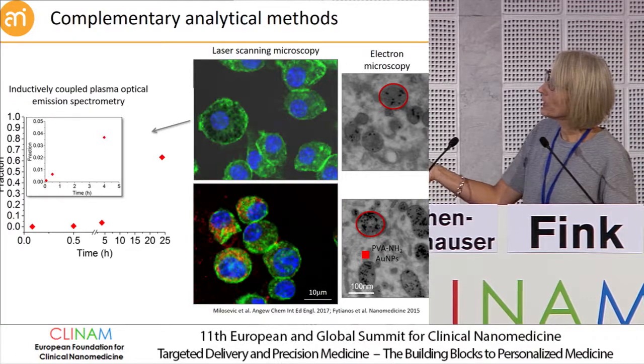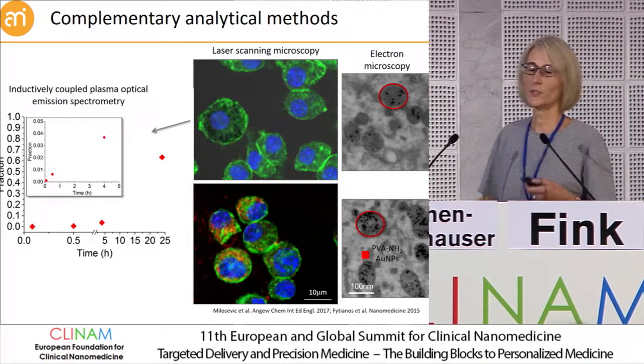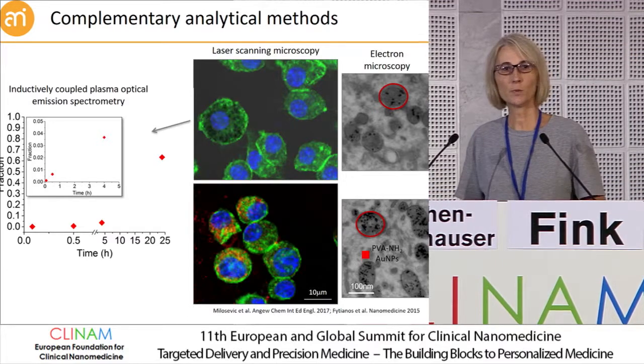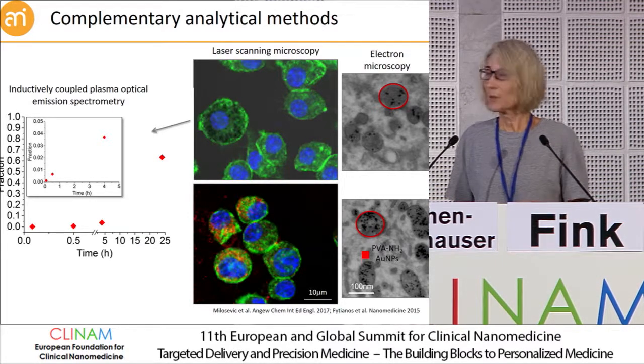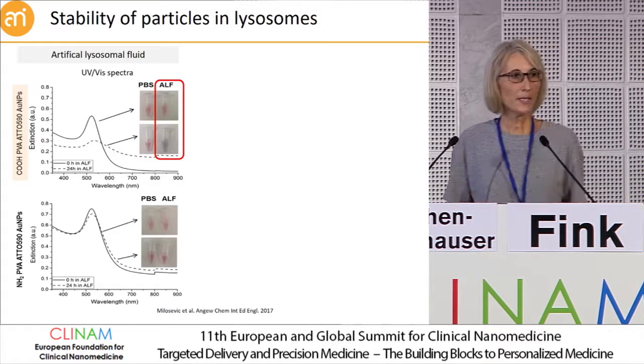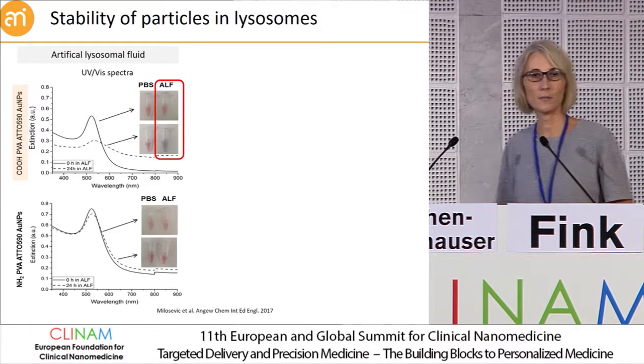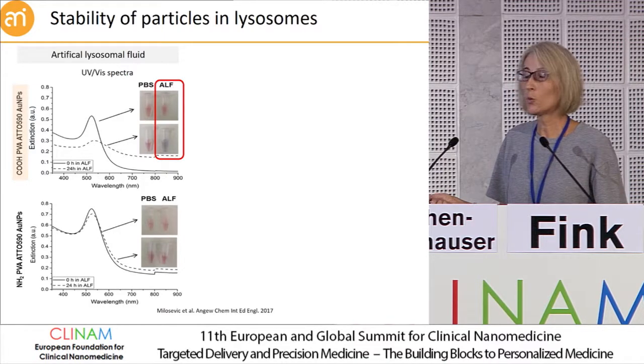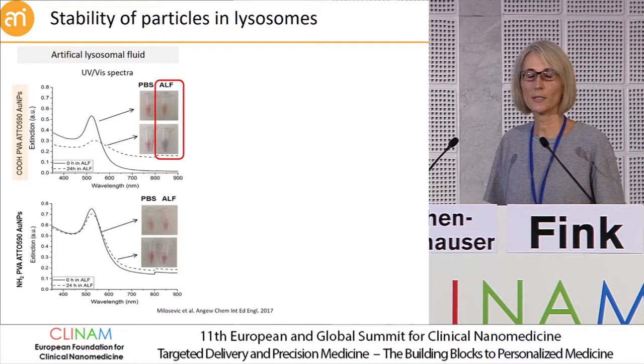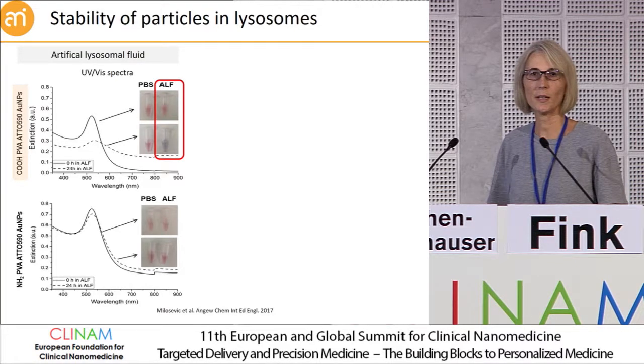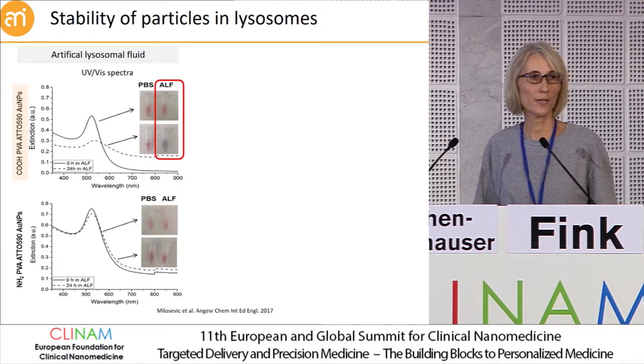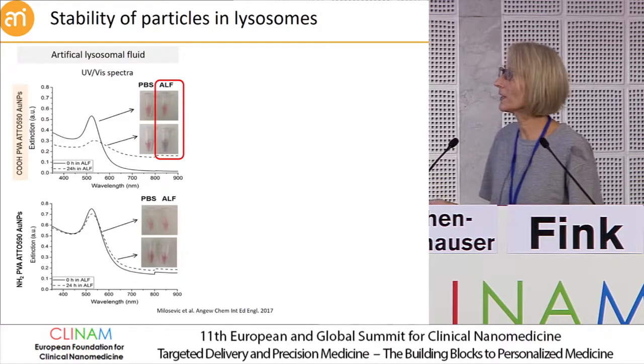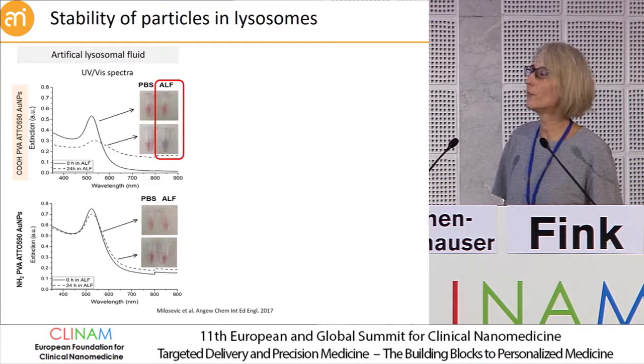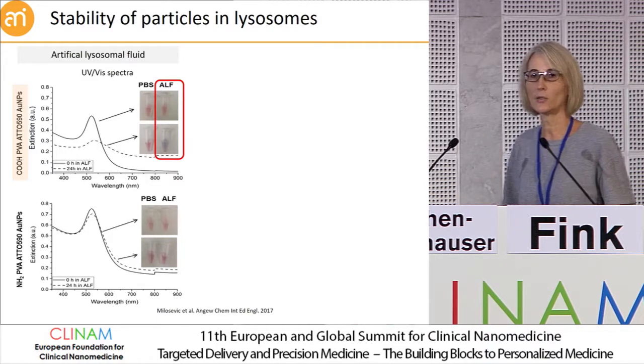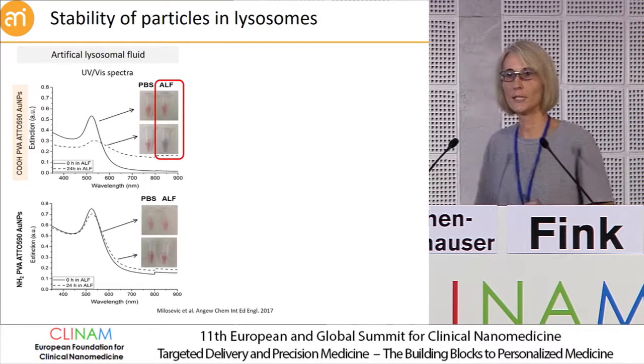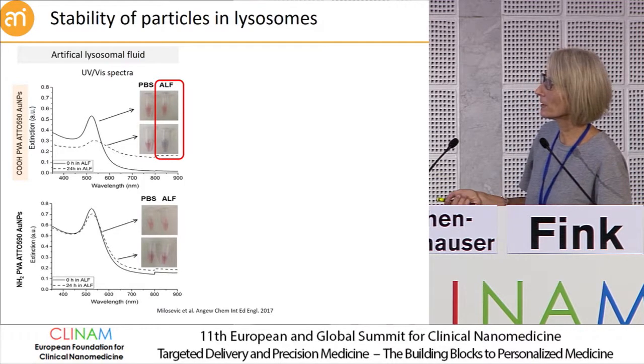So these pictures then started that we thought a little bit more in detail about this, and then we decided to investigate the stability and also the fluorescence at lower pH, because the endosomes and especially the lysosomes have a low pH between 4.5 and 5 and a very high ionic strength. So we mimic this lysosomal environment by producing this artificial lysosomal fluid. They do not have the enzymes, but all the other conditions are quite similar.